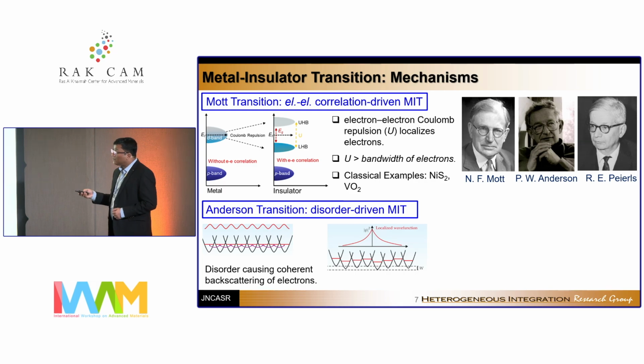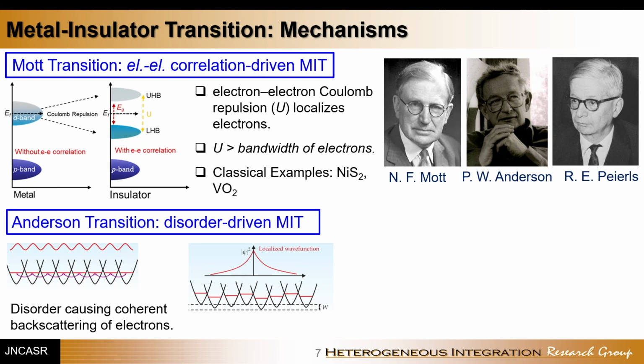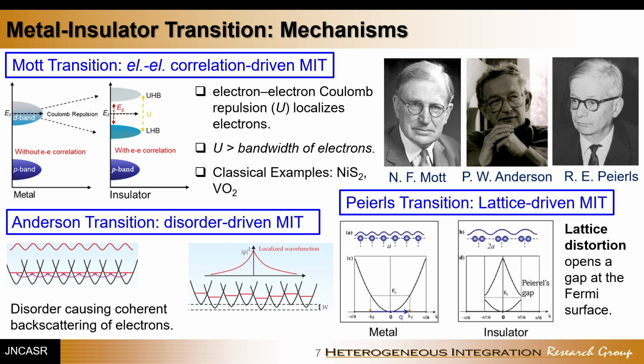In case of an Anderson transition or Anderson localization, you have defects in your crystal, defects in your material, where electron waves or any type of matter wave in their respective transport domain coherently backscatter, leading to a seizure of the propagation. So that's basically the Anderson transition. And in case of Peierls transition, that is basically the lattice distortion. In some materials, for example, charge density wave or similar materials, because of the lattice distortion, you have unit cell doubling that leads to a metal to insulator transition.